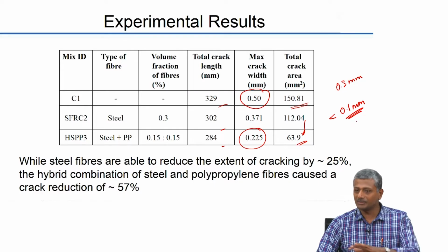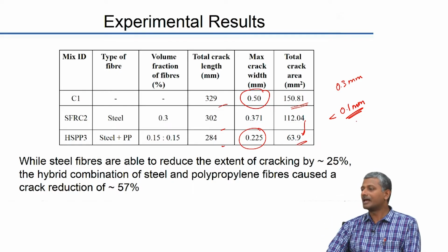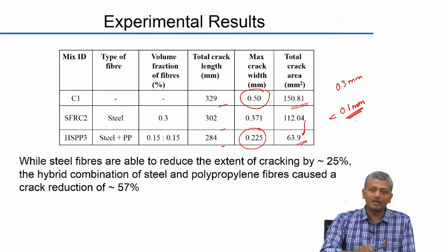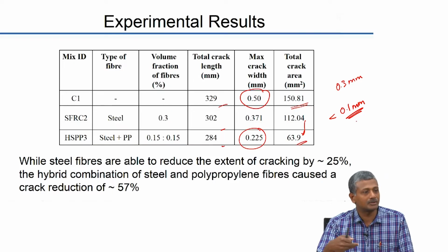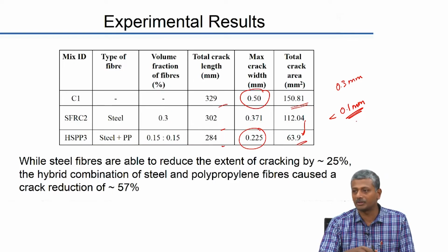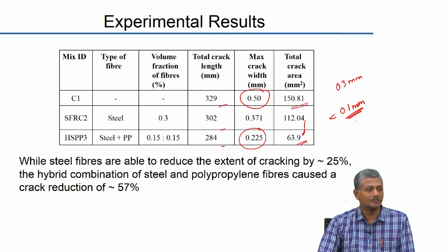They need to ensure that the first appearance of the cracks has to be detected, and floating can be done to actually remove the cracks, or completely covering the concrete to prevent evaporation needs to be done. Use of fibers, shrinkage reducing admixtures, of course it is effective, we can show all kinds of research to prove that, but ultimately it is a very expensive solution.